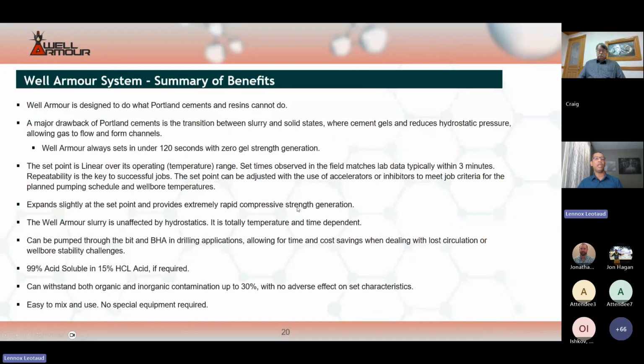In summary, the Well Armour is designed to do what Portland cements and resins, for example, cannot do. The Well Armour system always sets under 120 seconds with zero gel strength generation. The set point is pretty linear, as discussed or shown earlier, and the lab testing and the set point that's attained in the lab is pretty transferable to the field. We can achieve very low set time targets. We can also achieve very long set time targets if necessary, for example if we need to do a lubricate and bleed type operation or application.